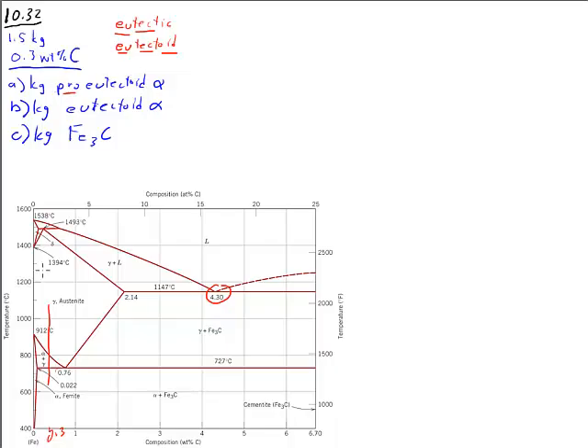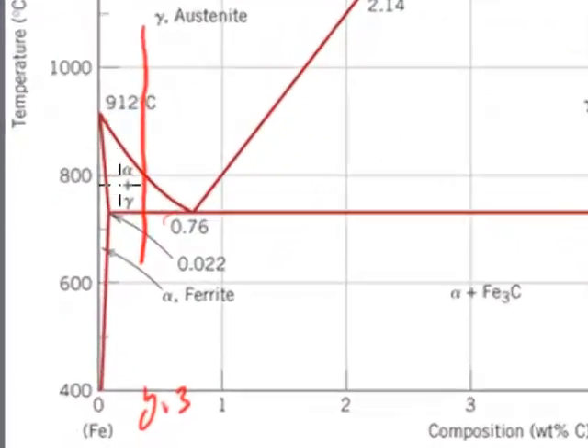So we need to apply the lever rule twice. First, we're going to apply it just above the eutectoid temperature. So our lever rule starts here, goes over to 0.76, and our overall length is from 0.76 to 0.022 right here. That's this location right there.